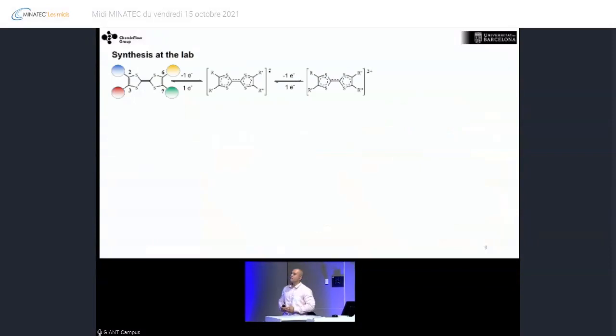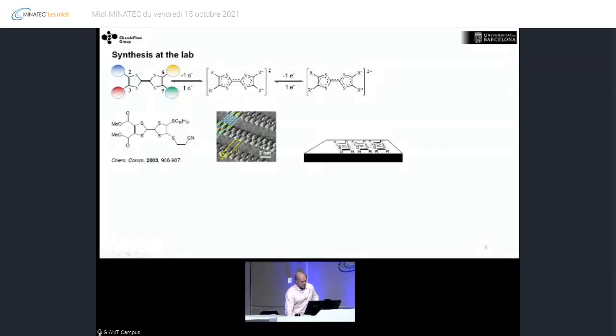This is basically the work that I did during my PhD. I was working with the tetrathiafulvalene, the TTF. This is a very well-known molecule in molecular electronics. And ideally, what you would like to have is to generate a pi-pi stacking of this molecule, because when it's partially oxidized, it allows conduction of holes through the structure. So this was the thing that I was doing during my PhD. So I was changing the functional groups in these positions in order to achieve this pi-pi stacking of the molecule.